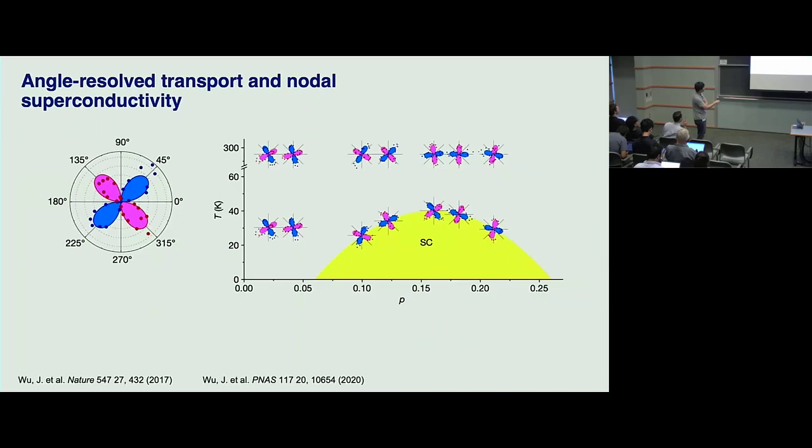this is close to room temperature, right? And because of the nature of cuprate, each one of these measurements is a different sample, right? So using many different samples, they can tune through the superconducting dome. And what their observation is this: in the normal state, close to room temperature, there is angular dependence, meaning that rotational symmetry is already broken at room temperature, so probably there's some kind of strain.